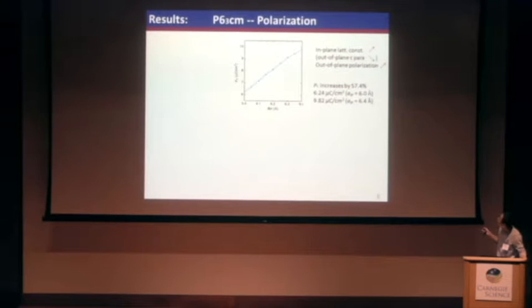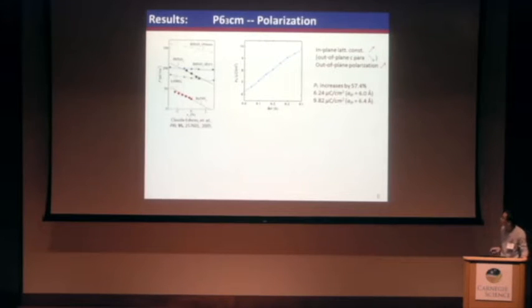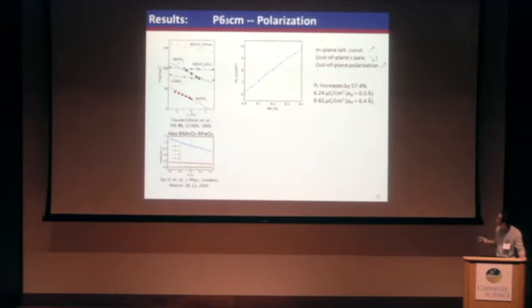It increased from this in-plane lattice constant for like 6 microcoulomb per square centimeter to this side. It's a 9 or almost 10. It's increased almost 60%. This is pretty novel because, according to our knowledge, normally when you increase the in-plane lattice constant, the out-of-plane polarization should decrease. But here it is increased. And also for the yttrium manganite type hexagonal structures, it is also like this. The polar mode decreases when the in-plane lattice constant increases.